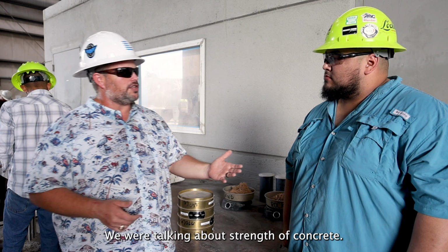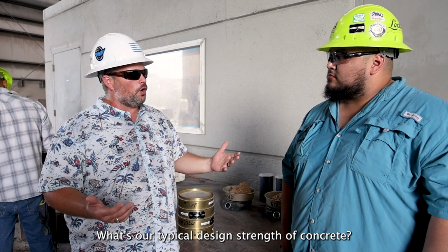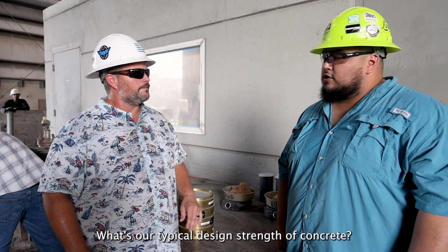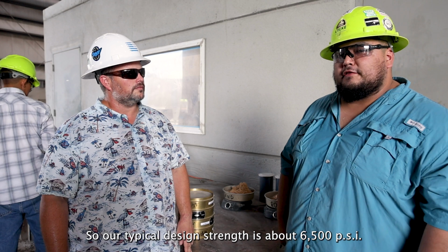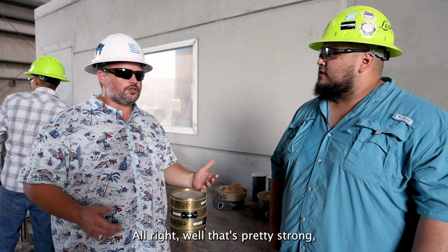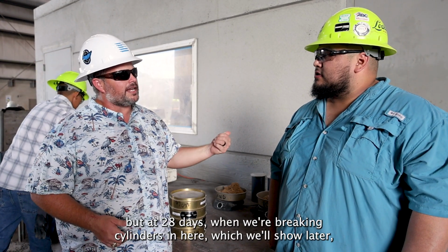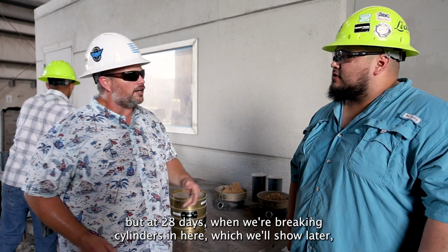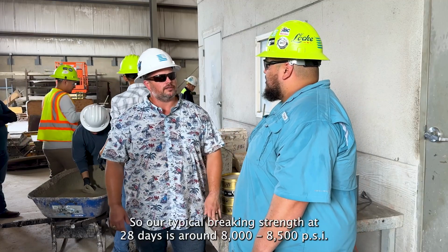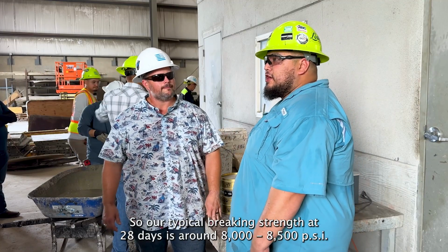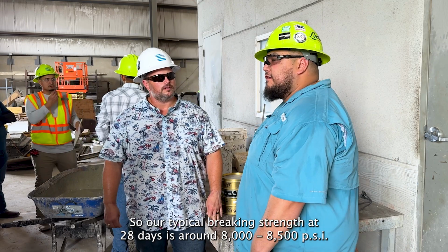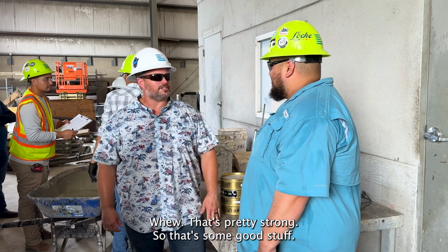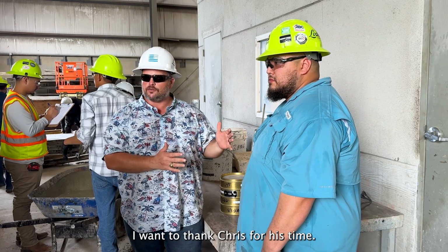We were talking about strength of concrete, what's our typical design strength of concrete? So our typical design strength is about 6,500 PSI. All right, well that's pretty strong, but at 28 days when we're breaking cylinders in here, which we'll show later, what is our typical breaking strength? So our typical breaking strength is at 28 days around 8,000 to 8,500 PSI. Woo, that's pretty strong, so that's some good stuff. I want to thank Chris for his time.